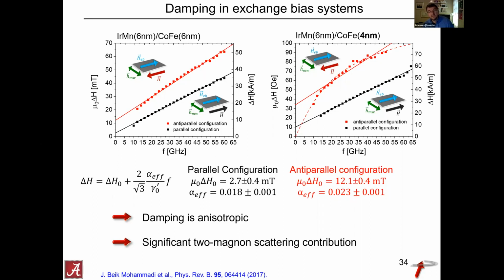What two magnon scattering typically has in common is that at low frequencies, you can describe it as approximately linear, whereas at high frequencies, at some point, it should saturate. So that's the common thing that you expect from two magnon scattering. The details then really depend on what model you use for the roughness at the interface.